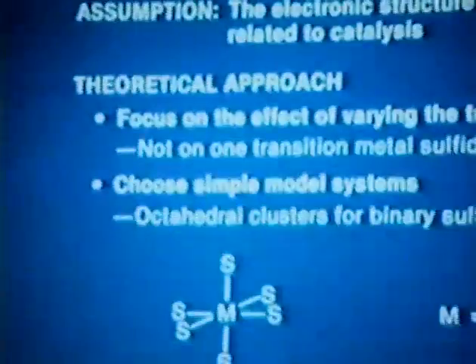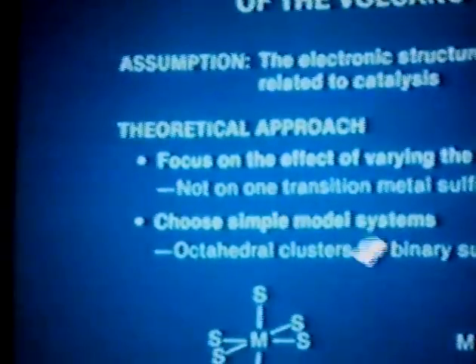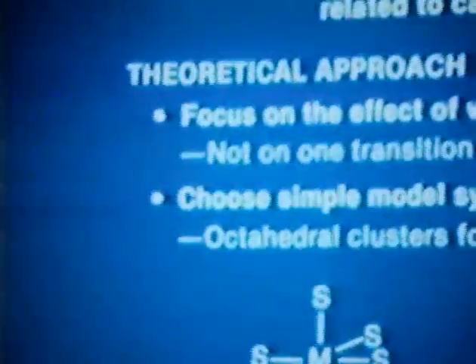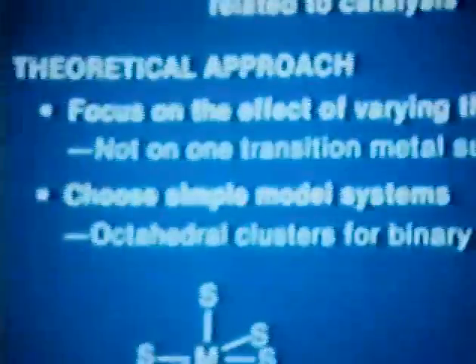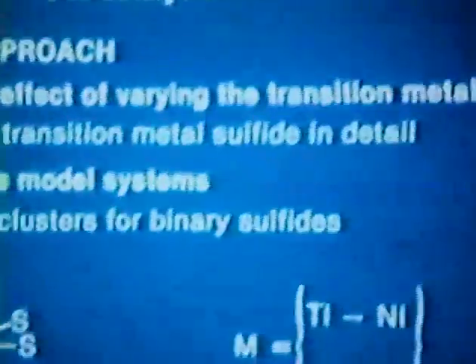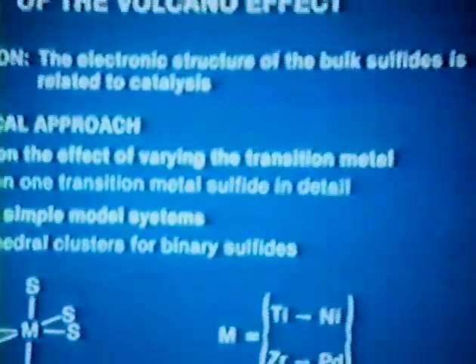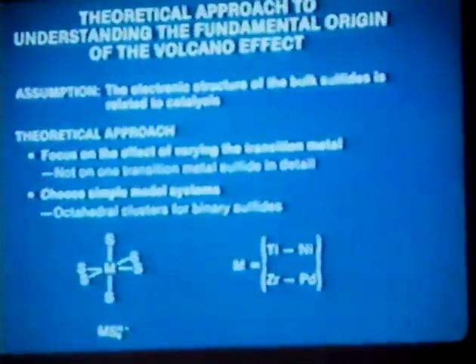But if you make that assumption and use a technique which we call scattered X-alpha calculations, it basically calculates the electronic structure of a hypothetical unit like this in an octahedral configuration, where the metal is titanium to nickel or zirconium to palladium. In this case, since structure is of secondary importance, we really want to focus on general electronic trends. You do these calculations and what you get is a set of molecular orbital diagrams like this, and you begin to fill them up with electrons.